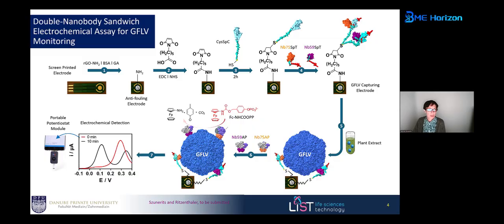So what we did, we used screen printing electrodes. We put antifouling agents onto this because one of the intrinsic problems in biosensors is always antifouling if you measure in very complex matrices, like in blood, but also in this case, in plant juice. So we got some nanochemistry based on reduced graphene oxide, BSA, and glutaraldehyde. So we get this on the interface. And then we use the remaining NH2 groups, which you have present on this NH2 enriched reduced graphene oxide and BSA, to do our chemistry.